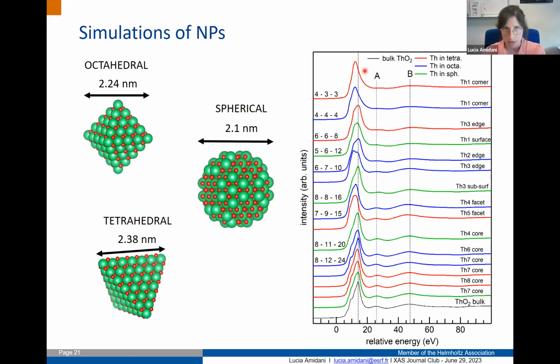In this part of the investigation, I tried different shapes of nanoparticles, those three shapes you see here. It may be a bit messy, but these are the atoms from those three shapes going from the bulk, the core, and then moving to the facets, subsurface, edge. You see a sort of continuity in how we go from the structure of the bulk, and little by little we lose the structures.